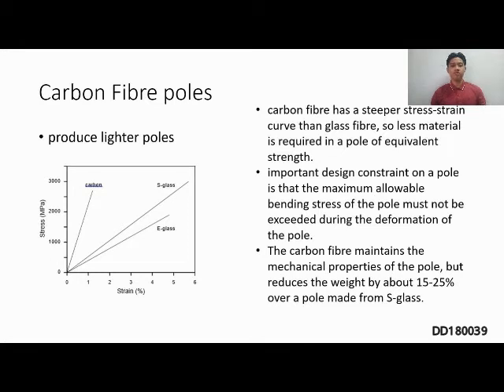Carbon fiber produces lighter poles. From the graph given, it can be shown that carbon fiber has a steeper stress strain curve than glass fiber. So, less material is needed for the carbon fiber in a pole of equivalent strength. Next, an important design constraint on a pole is that the maximum allowable bending stress of the pole must not be exceeded during the deformation of the pole. Lastly, the carbon fiber maintains the mechanical properties of the pole but reduces the weight by about 15 to 25% over a pole made from the glass fiber, which is S-glass.